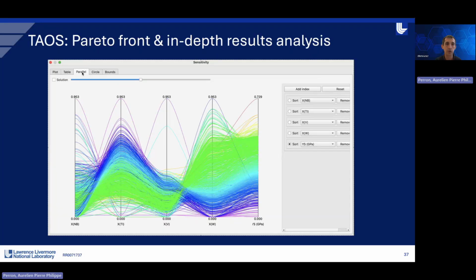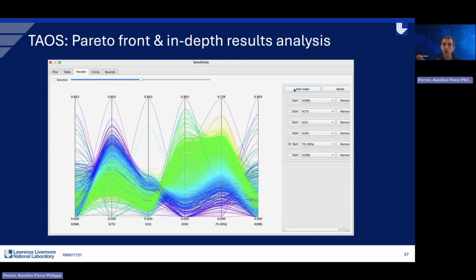Another thing that's nice to show, I think, is the relationship between the alloy composition and the properties. So here the yield strength is plotted. And if you follow, for instance, maximizing yield strength, the green line, you will see that you will have a tendency to maximize the tungsten contents while minimizing vanadium and titanium. But you can also add all the other properties that you calculated to see this kind of relationship. So here I added density because we wanted to minimize density. And you can see that for high density, yes, high yield strength, high tungsten content.